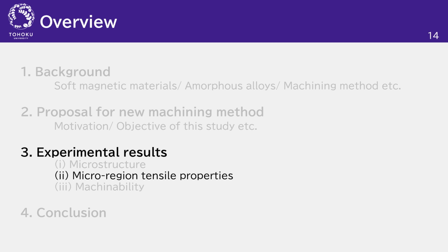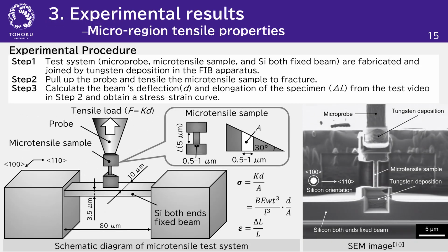Next, I performed microtensile tests on amorphous alloys heat-treated to various structures, and investigated the effect of microstructure on the mechanical properties in the microregion. In this study, we performed microtensile tests in the FIB apparatus. In this method, tensile properties are evaluated by applying the both-ends-fixed beam problem based on linear elastostatics.